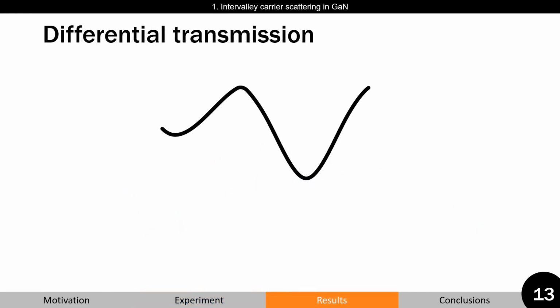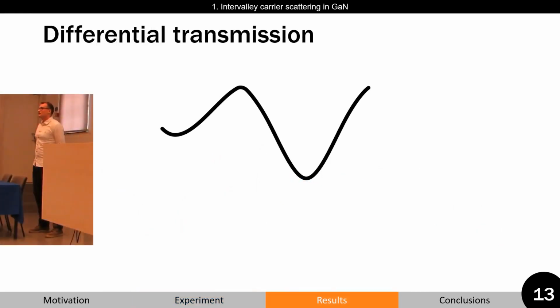I will start the results from differential transmission. Studied gallium nitride samples were unintentionally doped. In other words, at the bottom of the main conduction band, we had some peak carrier concentration. If our pump beam energy is below that of intervalley energy, one would expect to measure fast electron relaxation.